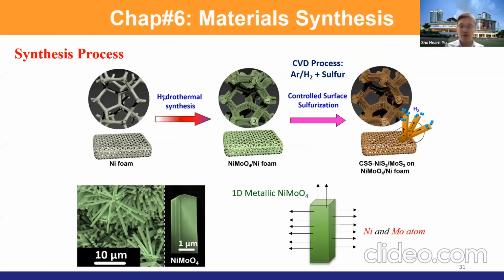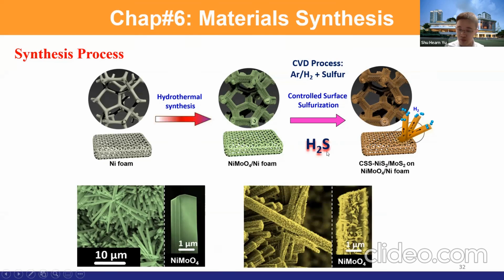And then if we perform controlled surface sulfurization on this nickel molybdenum oxide, the nickel and molybdenum will diffuse outward, and eventually react with the hydrogen sulfide, H2S, and form nickel sulfide and molybdenum sulfide. So these structures are not fully crystalline structures. If you control the time and the temperature, you can change the surface chemistry of this material.